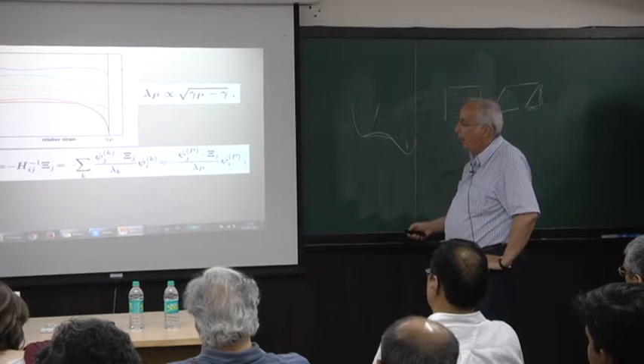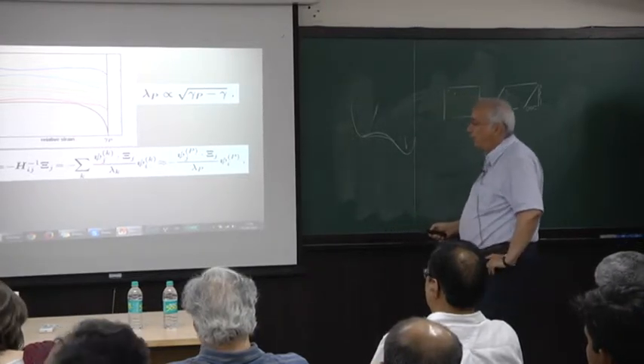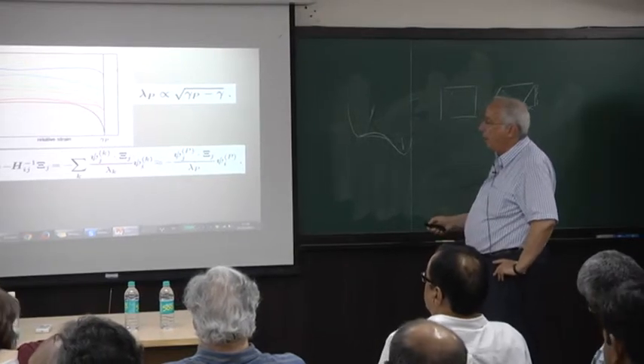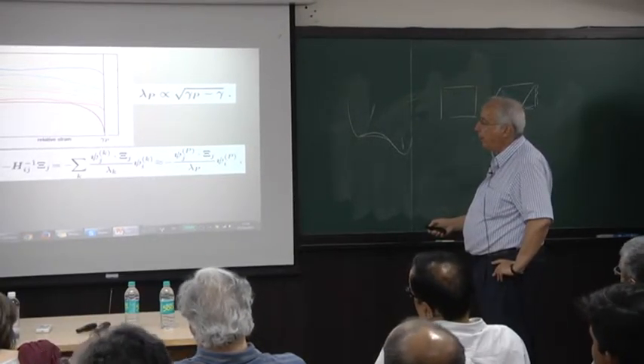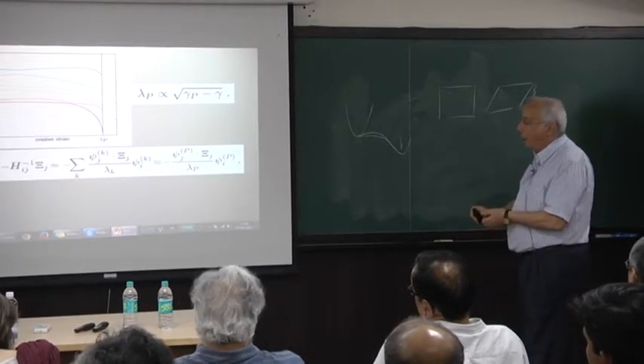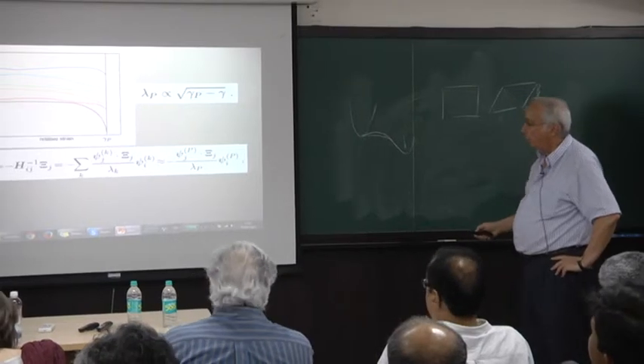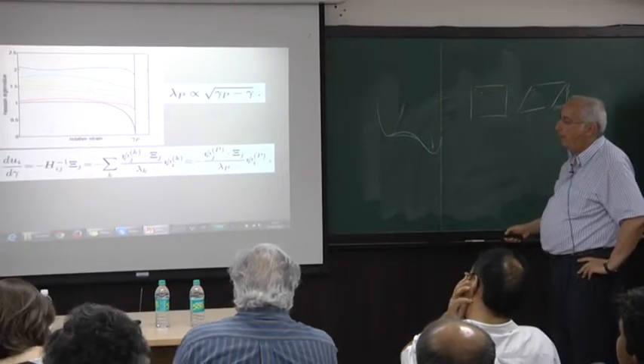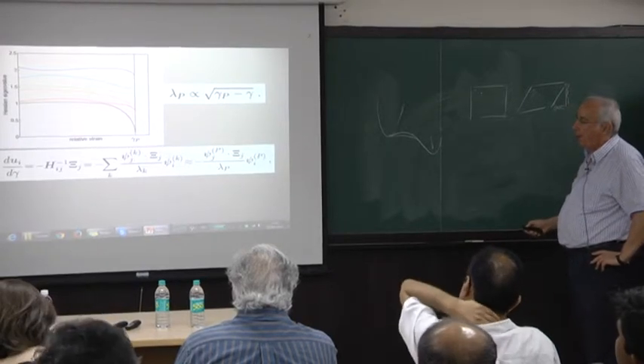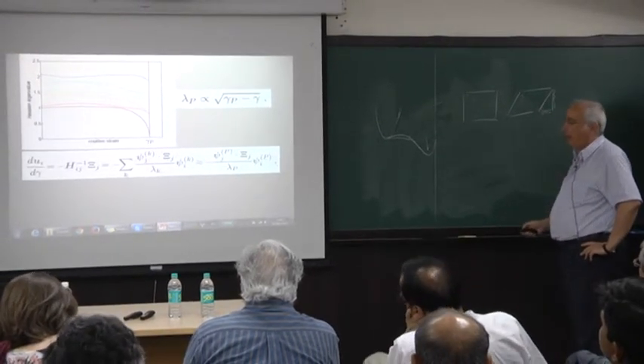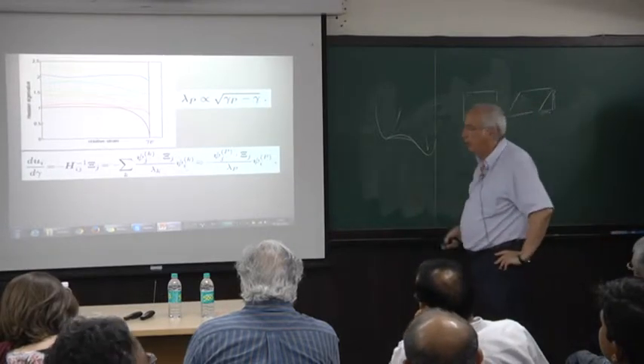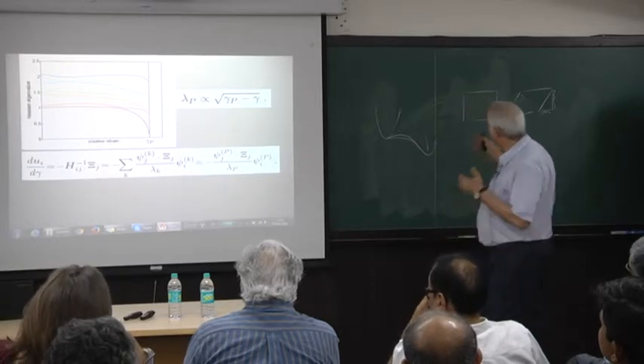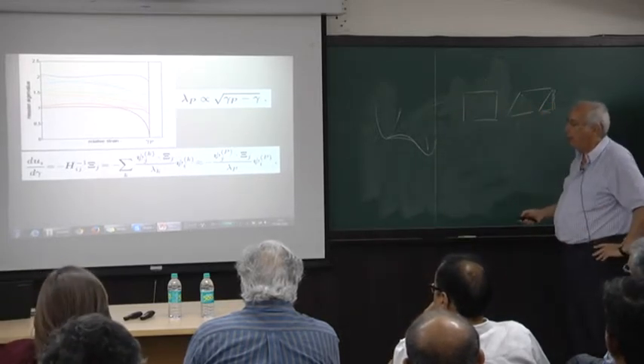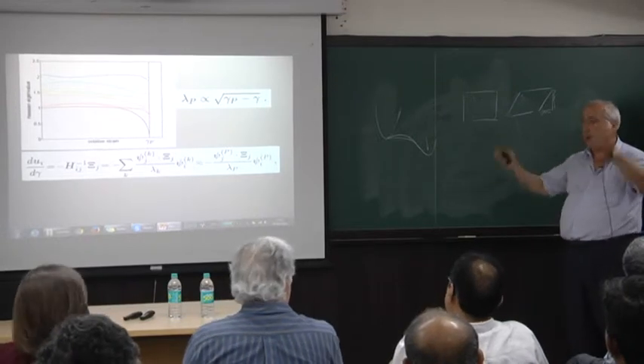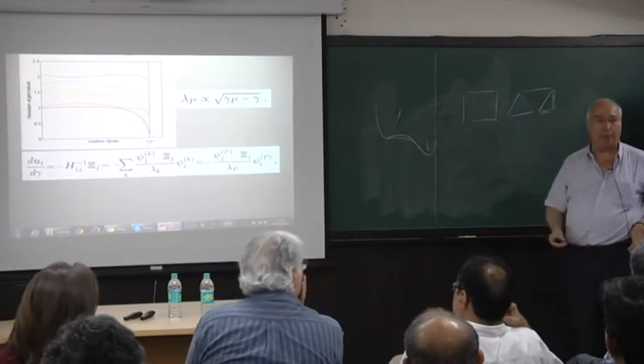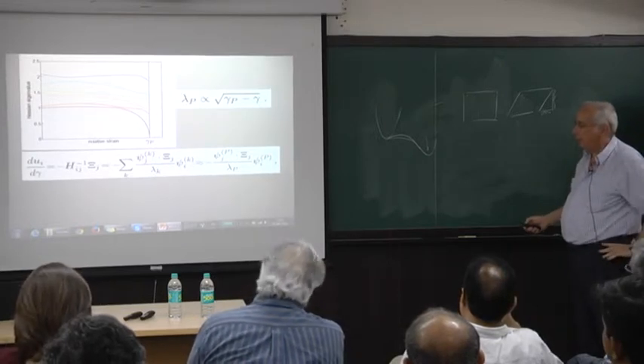This is the overlap times the function psi I over lambda k. And if one of the eigenvalues is going to 0, then sufficiently close to the instability there's going to be only one dominant term. We call it lambda p, the one that goes to 0. And then you now understand that the non-affine response is actually proportional to the eigenfunction of the Hessian that is associated with the eigenvalue that goes to 0. So this is really an interesting understanding of what the non-affine thing that occurs when you have an instability is: the motion of the particles under this non-affine response is dominated by the eigenfunction of the Hessian that is associated with zero eigenvalue.